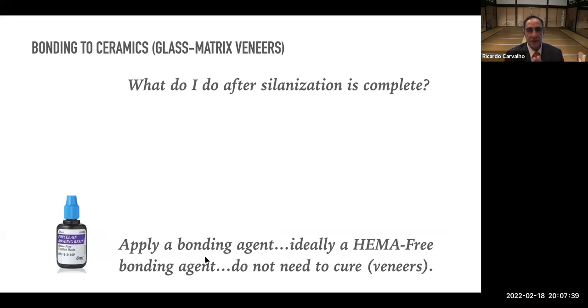If I do not apply it, if I go straight with my cement, well, I will get some bonding, but the cement itself is more viscous, and it will be hard for the cement and the particles to penetrate into those small porosities and accomplish better bonding. Some people recommend the bonding agent, ideally a hydrophobic, HEMA-free bonding agent, because as we know, some of these more, let's say, modern adhesive agents are highly hydrophilic. They contain a lot of solvents, and they are very permeable to water. And these might cause color change over time. And then, of course, it's not an issue for posterior teeth, but it might be an issue for veneers.